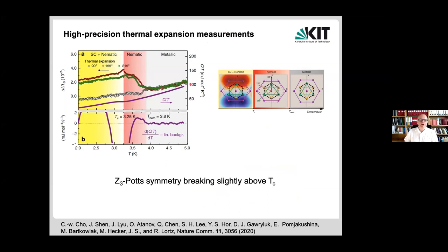Thermal expansion measures the length change of the sample. This is the superconducting transition. It has a tiny heat capacity anomaly, which is ultimately not too surprising because we have a low carrier concentration. But above that transition, one direction gets a tiny little bit shorter and the other two directions get longer. And you break the threefold rotation symmetry and you only have one axis preferred compared to the other.